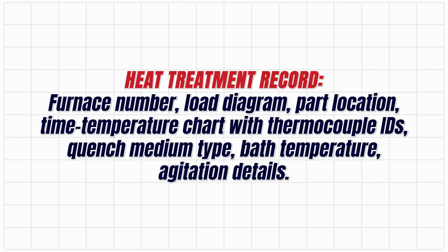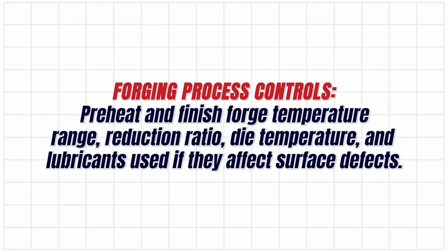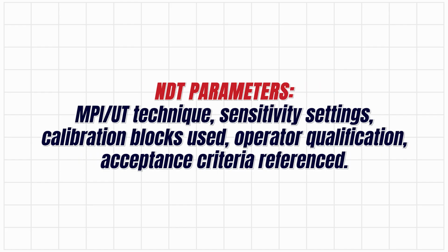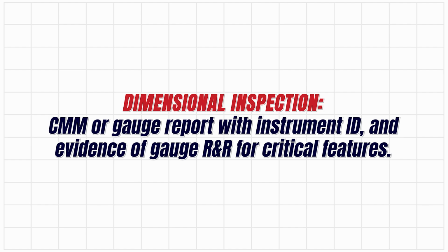Quench medium type, bath temperature, agitation details. Forging process controls, preheat and finish: forge temperature range, reduction ratio, die temperature, and lubricants used if they affect surface defects. NDT parameters: MPI, UT technique, sensitivity settings, calibration blocks used, operator qualification, acceptance criteria referenced. Dimensional inspection: CMM or gauge report with instrument ID and evidence of gauge R&R for critical features.